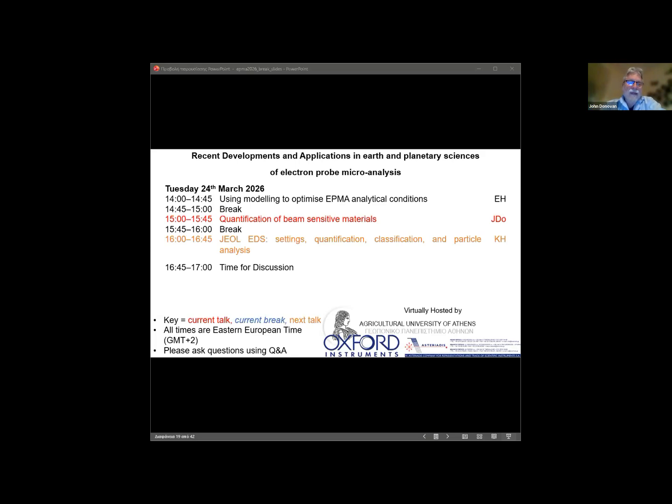In the case of the mapping, the TDI scanning, yes, you have to acquire multiple replicates, but normally where I would have done, say, for a quantitative analysis, 1 second per pixel or 500 milliseconds per pixel, you just do 100 milliseconds per pixel and do it 5 times. And the acquisition is the same amount of time. So, we can do this, and it's quite informative, as you say.